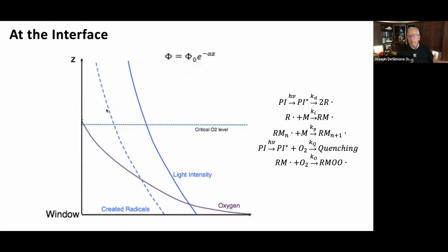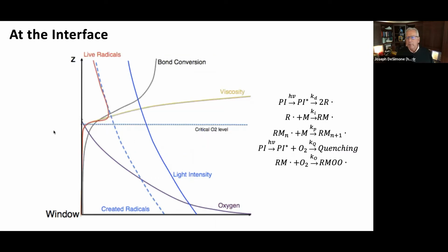Now that light that generates those radicals has one of two fates. They can kick off a polymerization, or if there's oxygen present, they will get consumed. And the rate of reaction with oxygen is far greater than the rate of initiation of a polymerization. And so what happens is those radicals closest to the window are consumed by the oxygen until the oxygen concentration gets below a certain threshold at which the polymerization will take place. So it's just like free radical polymerization. You want to kick it off, you degas your monomer. And this is what's basically happening as we kick this off.